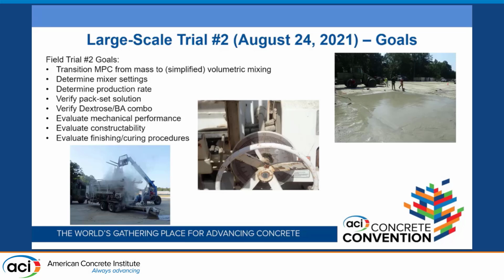So then we move on to our large-scale trial number 2. This was August 24th of 2021. The similar goals: transition MPC from mass to simplified volumetric mixing, and determine the mixer settings. I talked about the conveyor belt. This controls the gate at the conveyor belt, how much dry material is coming out, and then determine the production rate. Okay, can we do a 10-foot by 10-foot slab? Can we do a 20 by 20 slab? How big of a slab can we do? Verify that the pack set solution was actually solved. Verify the dextrose BA combo, evaluate the mechanical performance, constructability, and then also finishing and curing procedures once again.